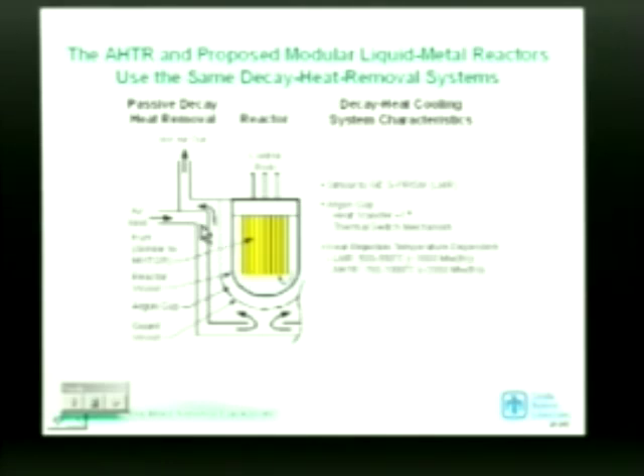The reactor vessel sits in a second vessel, a guard vessel. That's the second vessel here. And outside the guard vessel is the natural circulation of air from the atmosphere. Now, during normal operations, the amount of heat loss from the reactor to the outside environment is very low because the heat has to go from the primary reactor vessel to the guard vessel. And between these two vessels is about 4 inches of argon gas. The only way the heat can go across here is by radiation heat transfer.